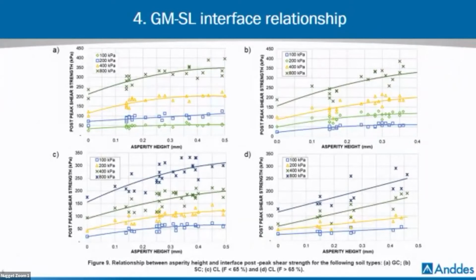For the interface with geomembrane and soil liner, we can do the same, but the empirical formula, in this case for textured geomembrane with soil liner, was obtained considering the influence of the asperity height of the geomembrane and the kind of soil. The previous results, or the combination of results, could be used to run a preliminary slope stability analysis of heap leach pads for block failure.